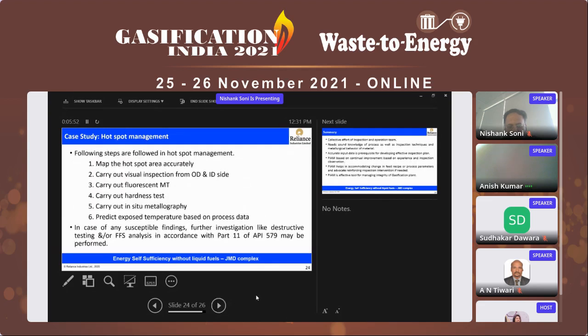Moving to the next slide, we will discuss the steps that need to be followed to manage a hotspot. After taking a safe shutdown, we have to map the hotspot area very accurately and carry out visual inspection from both the ID side and the OD side, to check for any bulging or deformation in the metal surface. After that, we will carry out a fluorescent MPT, which is ideal to examine any surface crack propagation. And after that, we will do a hardness test, which is also ideal to check any changes or degradation in the mechanical properties of that exposed part.